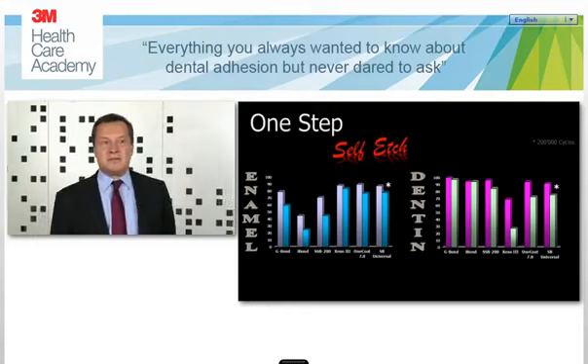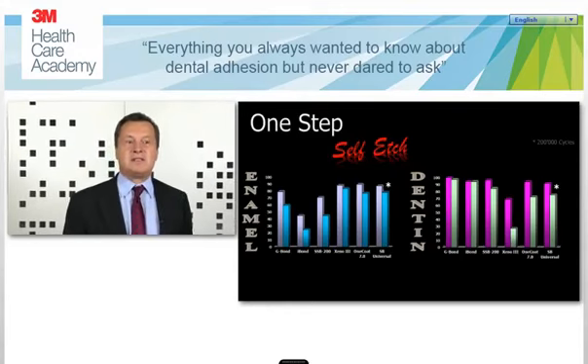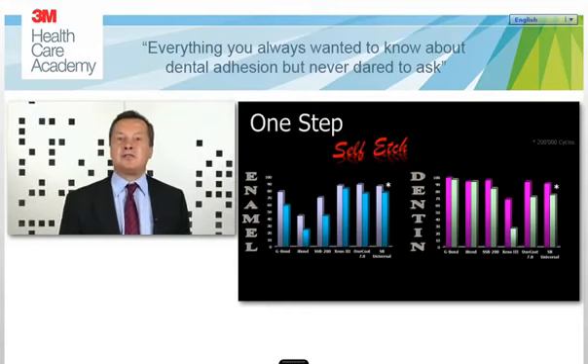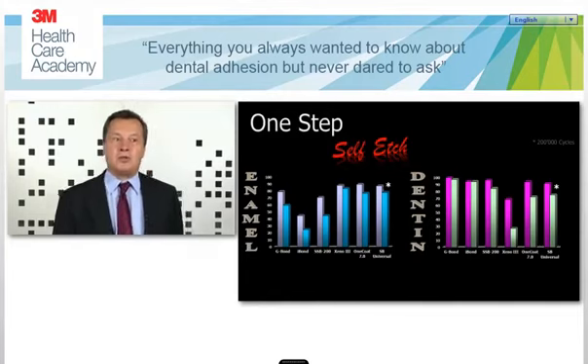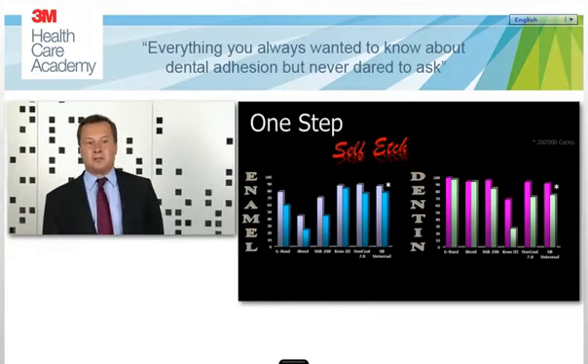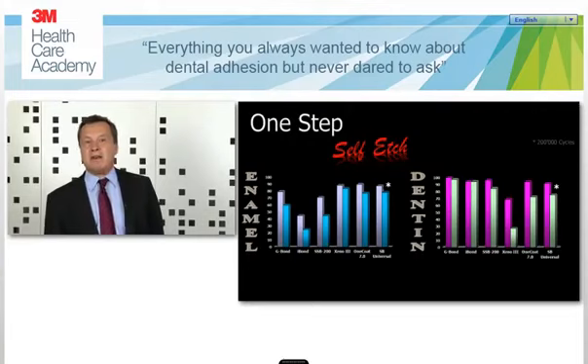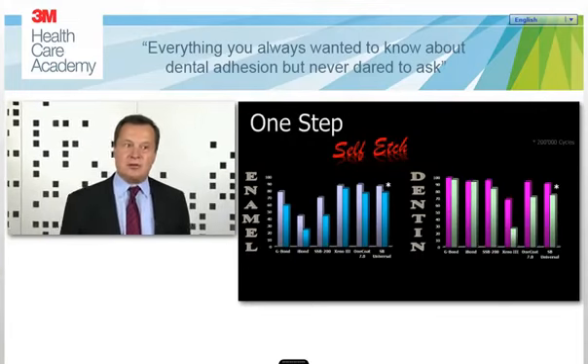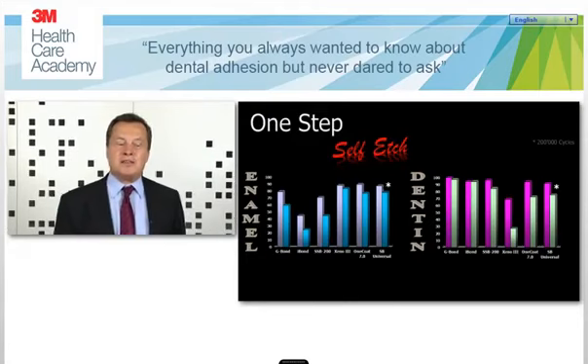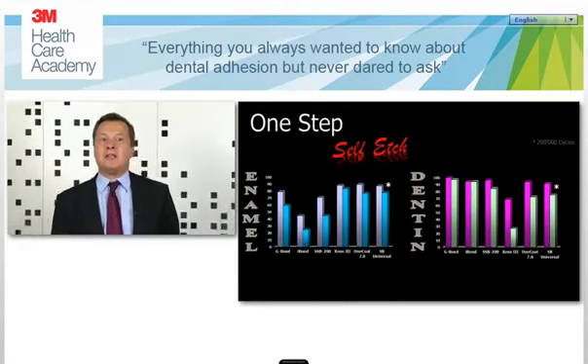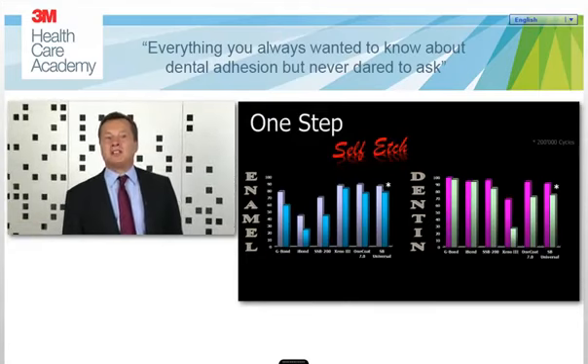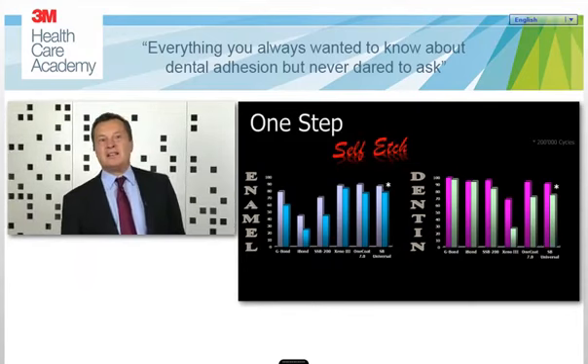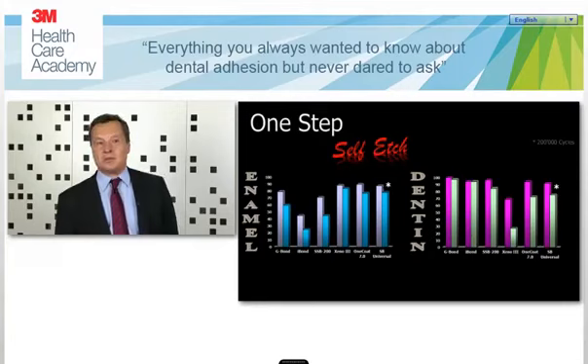The contrary, just to give you an example based on this graph, is Xeno III, also the old version of Xeno III, not the actual version. Here it is the contrary. Apparently this material used quite aggressive acid for conditioning, which at the end led to quite good marginal adaptation on enamel, but it apparently over-etched dentin. This is why dentin adhesion was quite weak, or the marginal adaptation on dentin was not optimal.